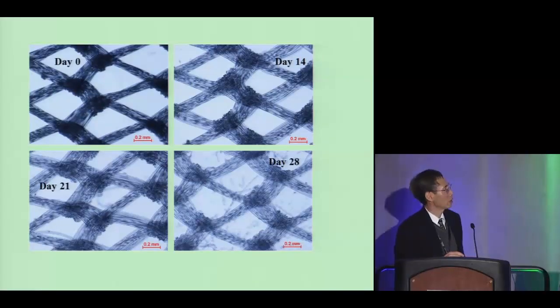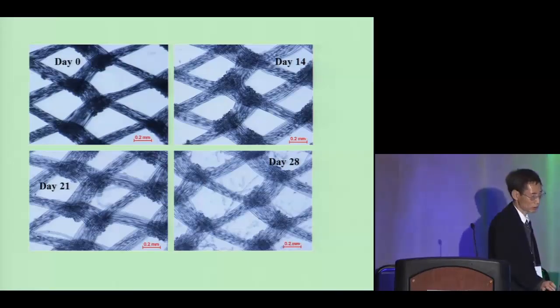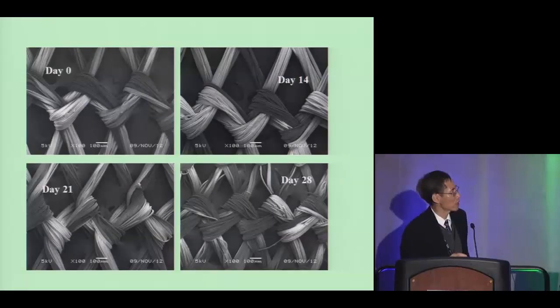Yeah, this slide shows optical microscopy of the mesh, I mean the light mesh. Basically, it's hard to see any change after 4 weeks. The reason we took it just up to 4 weeks is that the main thing in the study was mechanical property change. You see some fiber breakage, but very few. Yeah, we also sent the samples for SEM, with similar results to the optical microscopy.